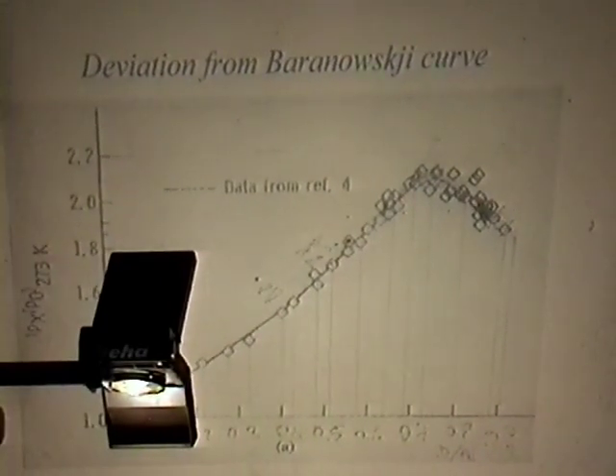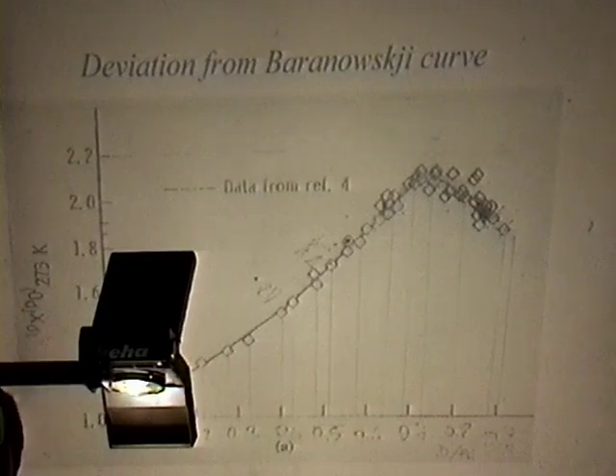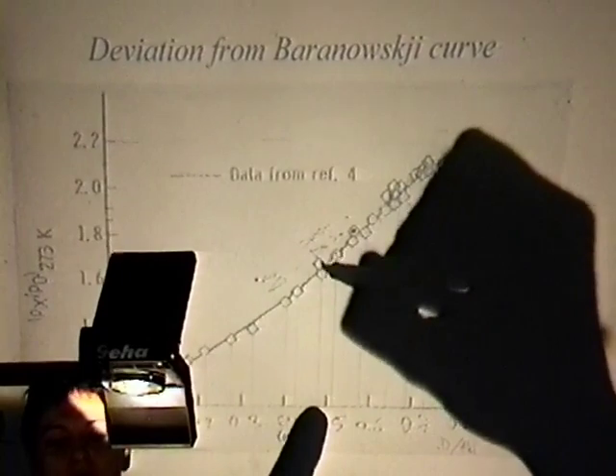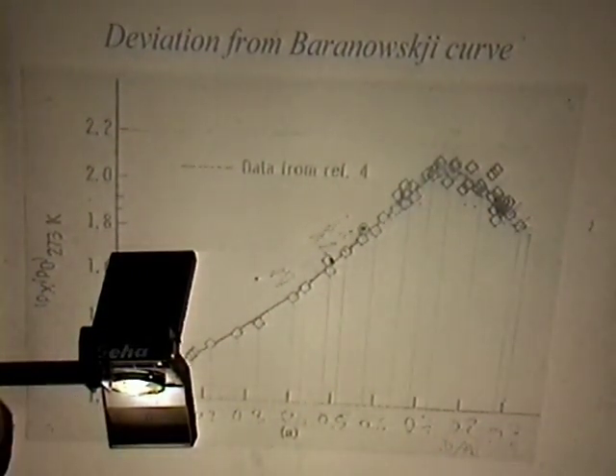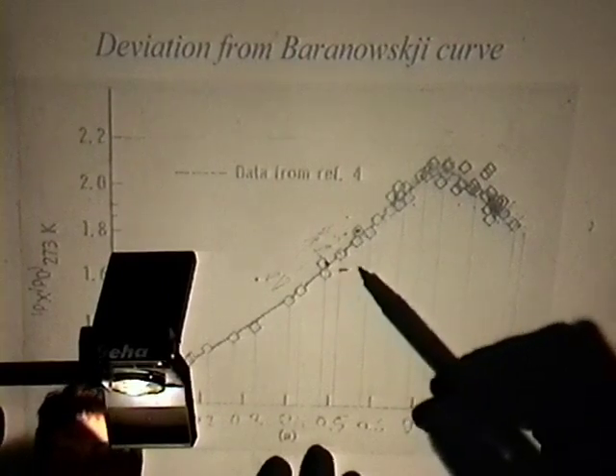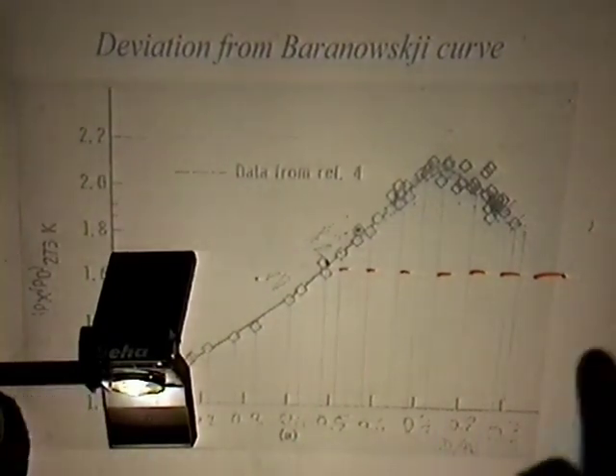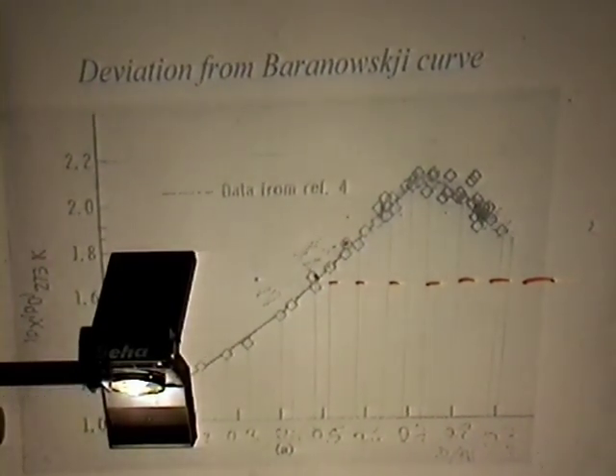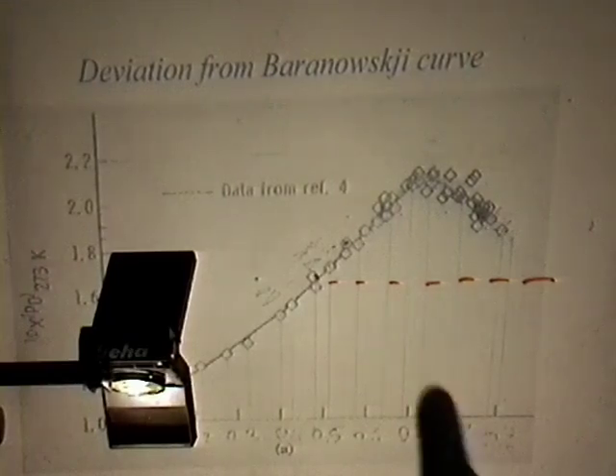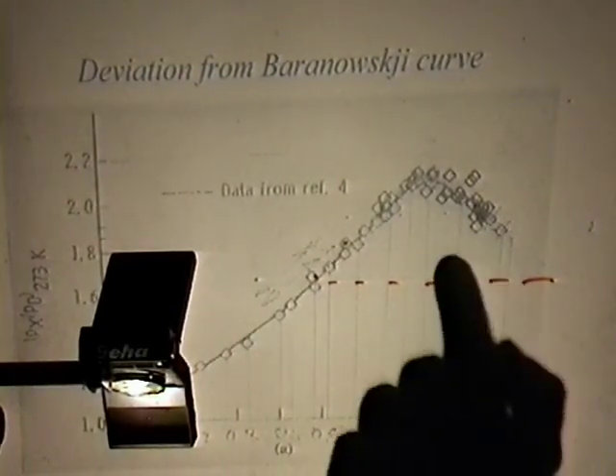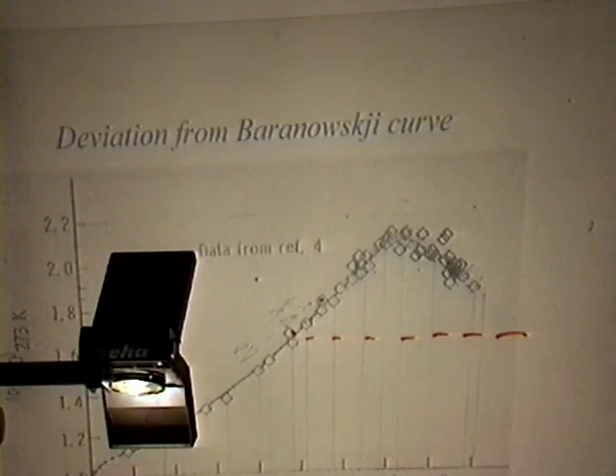So what happens? This is the old famous Baranowski curve. If it starts to nucleate a new phase at a lower concentration, let's say 0.5, it depends. This is just a qualitative sketch. We don't have the numbers to put inside our frame yet. We hope to do better next month. But if at this point we leave the Baranowski curve, then we are again on the Baranowski curve on the other side. So the system tunnels through the Baranowski curve, because in this region we again have a phase coexistence between beta and gamma phase. This is very similar to what we see in our measurements. There is something similar in literature as well.